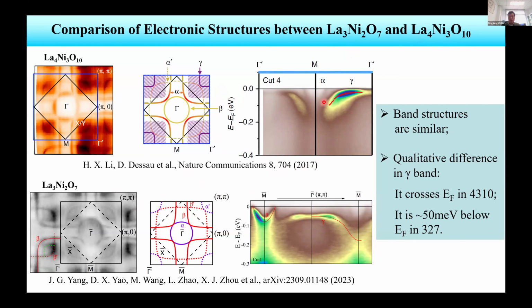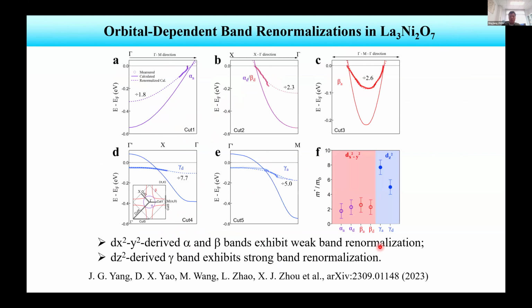In 4-3-10, the gamma band crosses the Fermi level, but in 3-2-7, it's below the Fermi level. I think that's the main difference. Eventually, we also measured the orbital-dependent band renormalization in the 3-2-7 system. Mainly we have alpha bands, beta bands, and also the gamma bands. We measure the band renormalization either along the axis or along the diagonal direction.